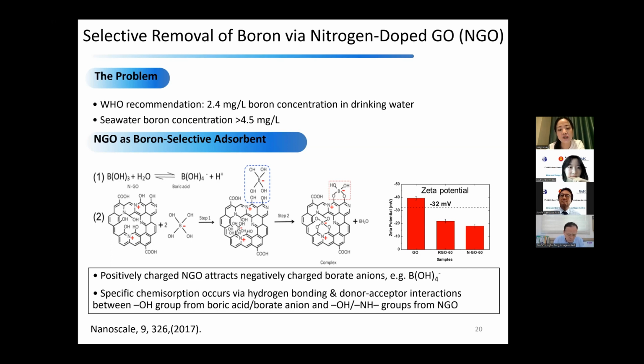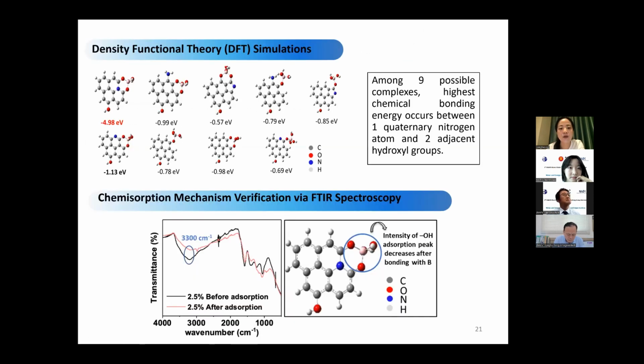We can use this absorption technology through this nitrogen-doped graphene to realize the full removal of this boric acid or boron in the seawater. And then we have also figured out the different positions that the nitrogen can be embedded into this structure. So there are in total 9 possible complexes. And we can see that one of them, as we highlight at this left corner over here, has 1 quaternary nitrogen atom and 2 adjacent hydroxy groups that will have the highest energy, and that will have the most attractive force towards the boric acid.